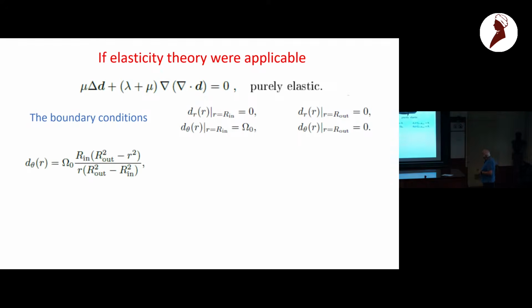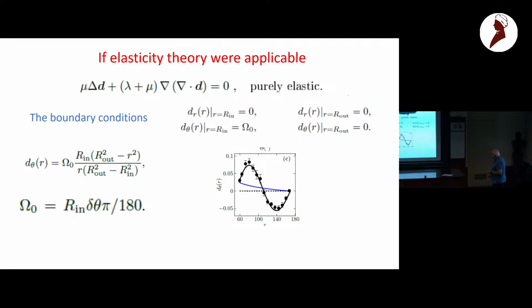So you have an exact solution that you can immediately write down for the angular displacement as a function of R. It looks like this. It solves the boundary conditions, and the number here is determined by how you do this delta theta. So it's a very small omega 0 because delta theta is small and you have a factor of 180 here, etc. So this is the result, the blue line. The blue line is what you expect, and of course the conclusion is that it is a clearly wrong prediction. So you need to come up with a different theory.